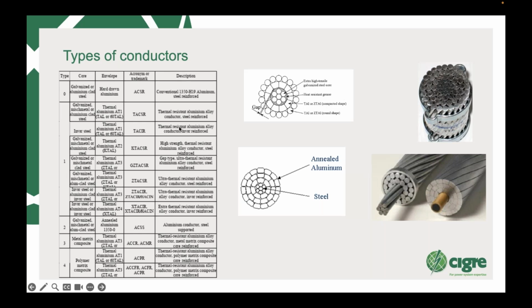Now, these are the kind of conductors that I was mentioning. This is mentioned in a number of the CIGRE brochures. Basically, what we normally use is ACSR, so most common. You then get a thermal resistant ACSR, which is steel reinforced. You can then get a thermal resistant aluminium alloy, which is INVAR reinforced. INVAR means invariable, and it's really a certain alloy of steel, which doesn't vary much with temperature. You can then get a high strength thermal resistant aluminium alloy, steel reinforced. Then you can also get what's called the gap conductor, which is shown here in this diagram.